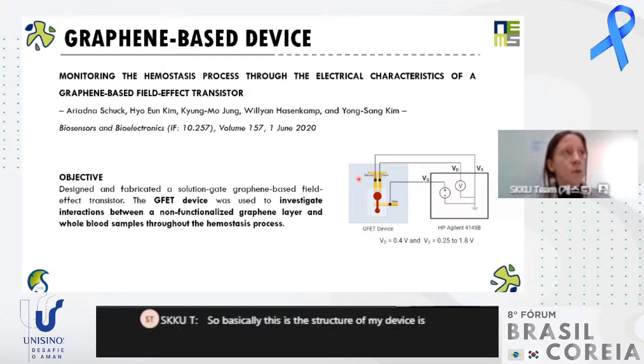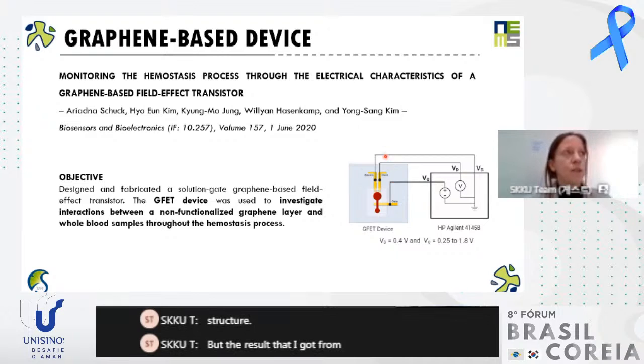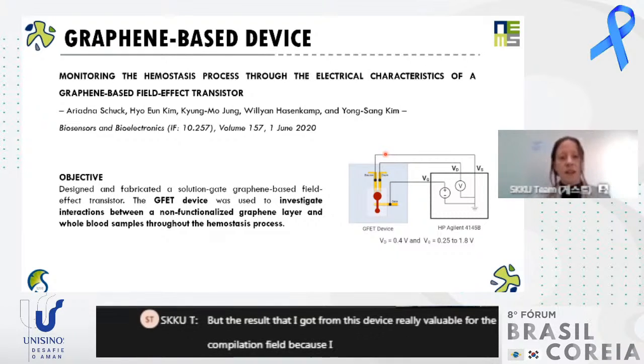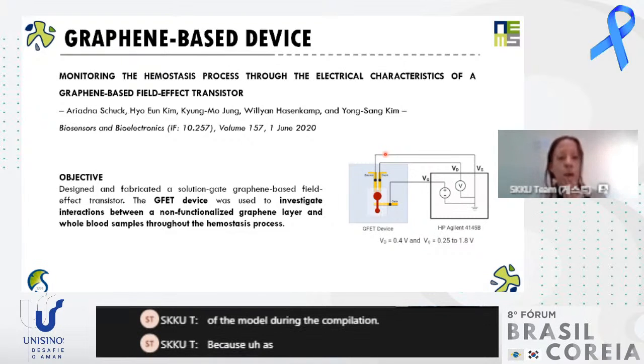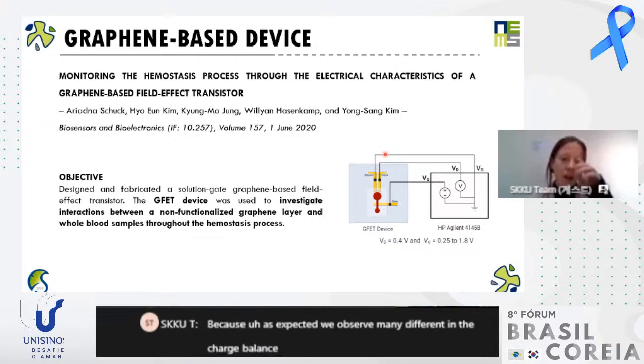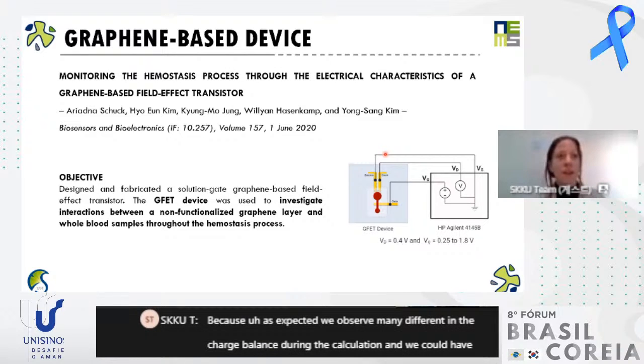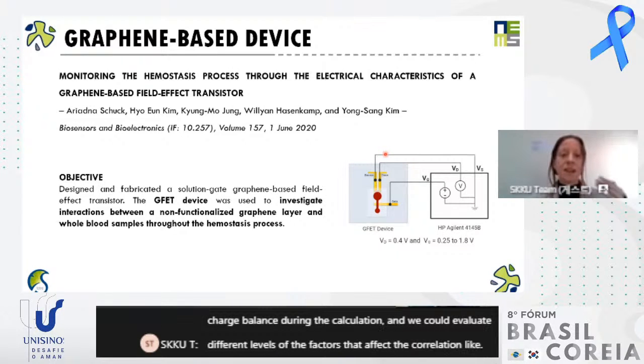Basically, this is the structure of my device. It's a really simple structure, but the result I got from this device is really valuable for the coagulation field because I was evaluating the electrical properties of the blood during coagulation. As expected, we observed many differences in the charge balance during coagulation, and we could evaluate different levels of the factors that affect coagulation, like those that accelerate the process and those that slow it down.